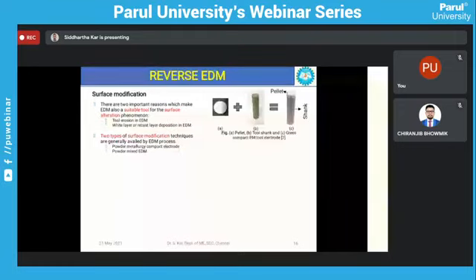For the powder metallurgy electrode, here in the diagram a pellet is shown, composed of the powders that we intend to deposit on the workpiece surface. That pellet will be made, then glued by a conductive paste to the original tool. Then this will be used as the tool electrode. This process is known as the powder metallurgy tool electrode. This is an example where tungsten and copper have been deposited successfully over C40 steel. We can see that a very thick layer of deposition has taken place over the steel surface.